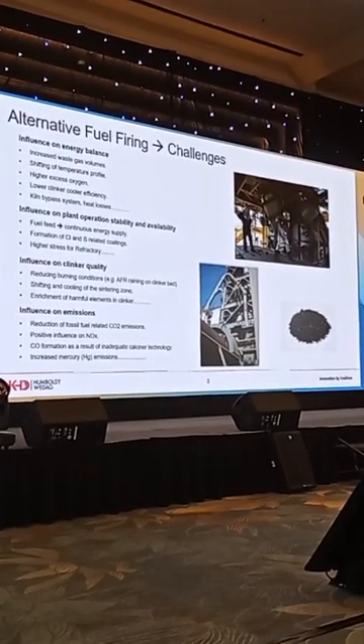But not only all these negative effects that I've just talked about are influencing the usage of alternative fuels. There are also some positive effects by using alternative fuels. You are reducing the CO2 footprint because you're not using the standard fossil fuels, which are normally used here in Vietnam, for example, coal or natural gas and so on. So the CO2 footprint is definitely reduced by using alternative fuels, which is already now a high demand on the market. And another positive effect is that by burning the alternative fuels with a lean gas in a CO-rich environment, the NOx emissions are also reduced by a positive reaction of the carbon monoxide created just from the burning process.